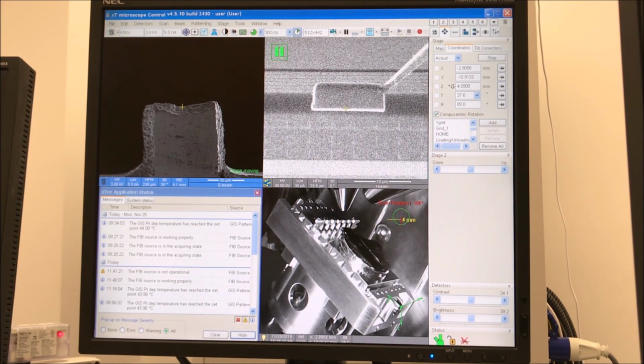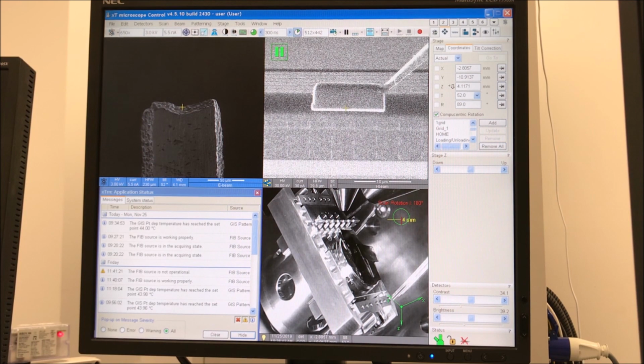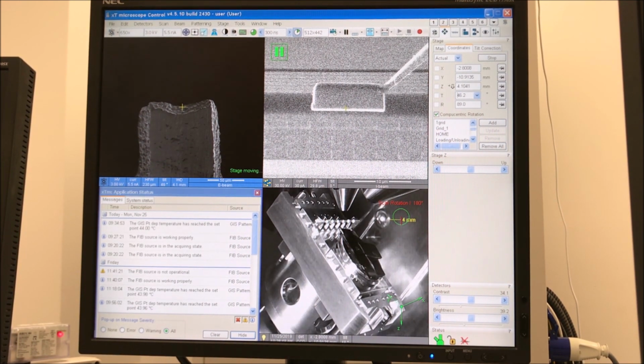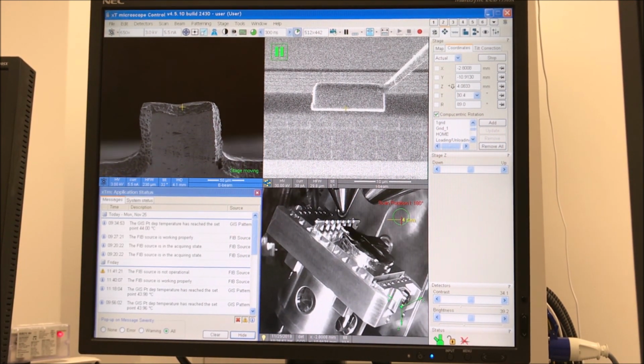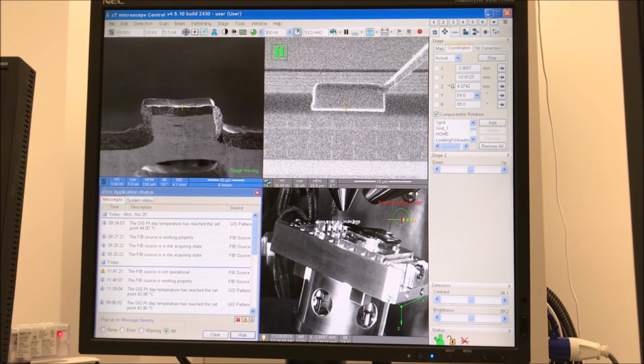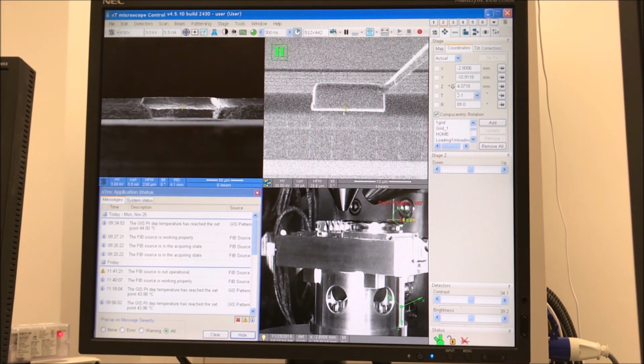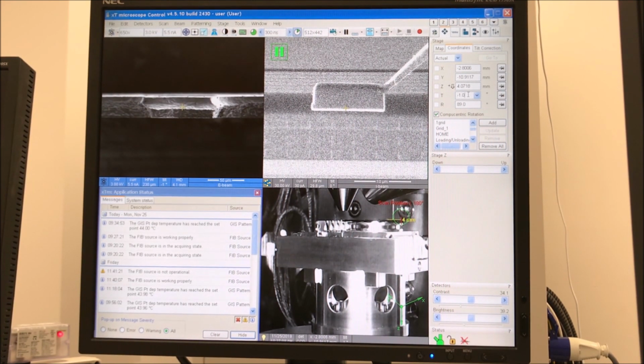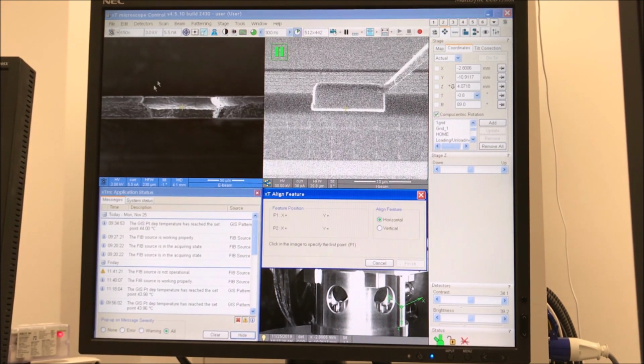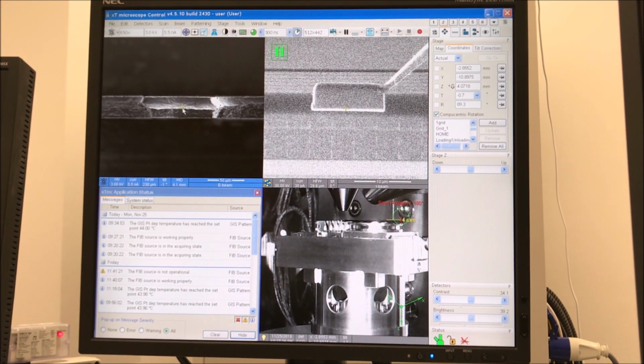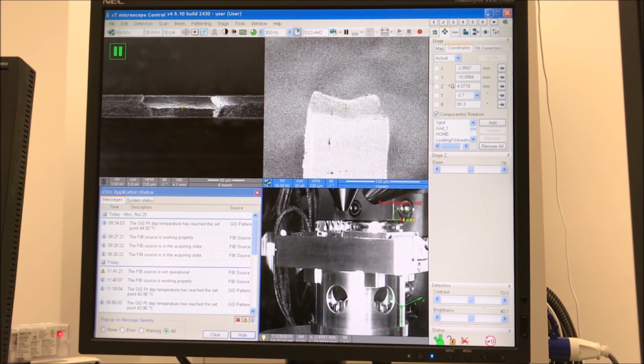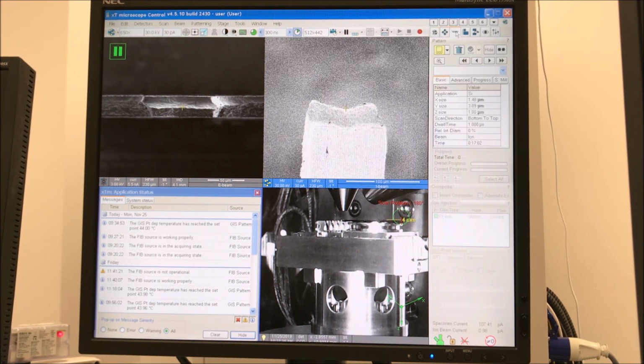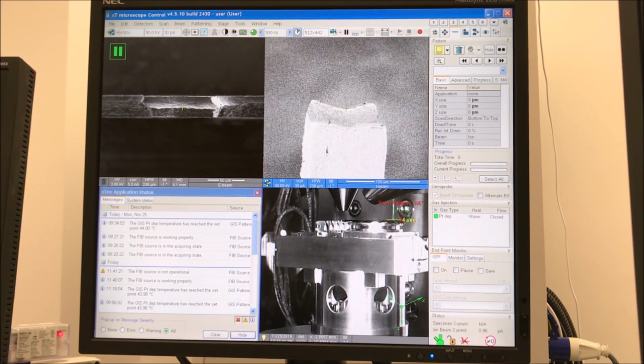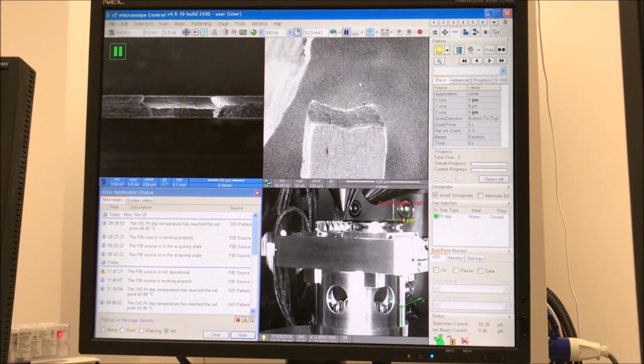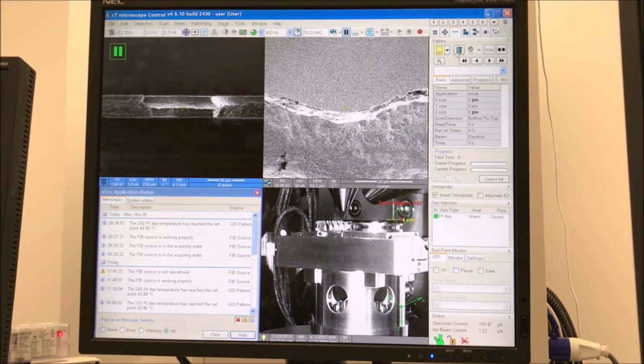There are different places that people attach lamellas. I prefer to attach them in the middle. Some people will attach them on the sides, but I prefer to do it this way. I'll get into that in greater detail a little bit later. So you can also see that the grid isn't perfectly edge-on, so I'm going to do a manual adjustment of the tilt until it's perfectly aligned, and I'm looking straight on edge. And so that was about minus 0.7 degrees. And now I'm inserting the platinum GIS and the omniprobe.